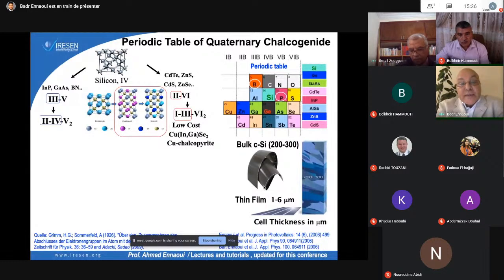Those that work on 3-5 compounds are rather sophisticated, and they try to use very expensive equipment to make this material, like epitaxy, etc. When you go from the 2-6 compound or 3-5 compound, you can go to ternary compounds. And here also the research on 2-6 compounds will move you to low cost materials like chalcopyrite, copper indium gallium selenide. However, if you work on gallium arsenide, for example, which is very expensive, you can move to infrared detectors. And this kind of research on 3-5 compounds was developed rather during the Cold War in the military sector, because you can prepare very good infrared detectors. So the military has a lot of money, and at the university there is less money.